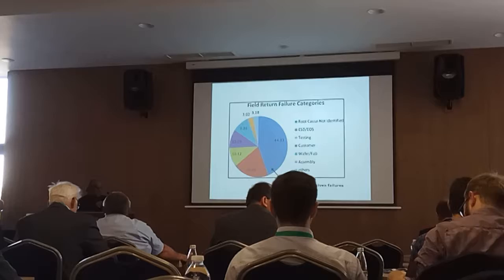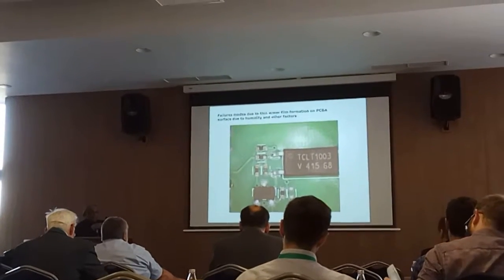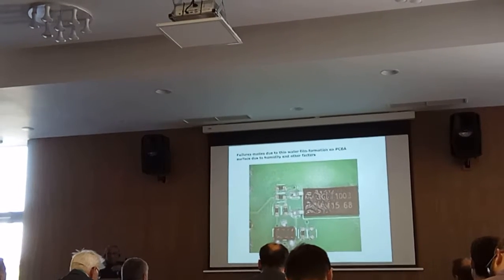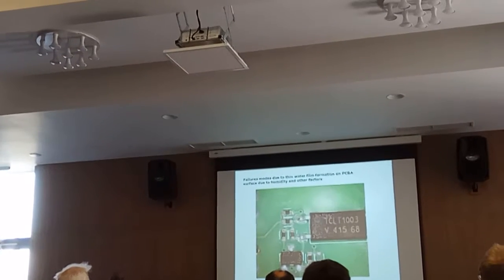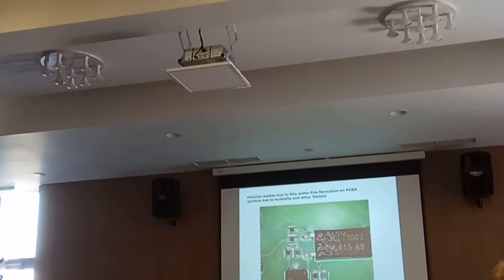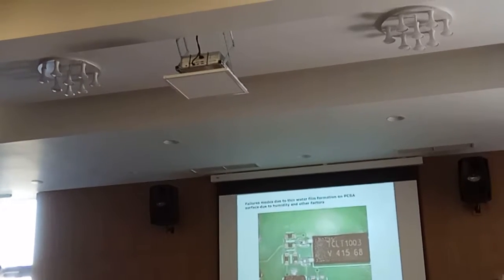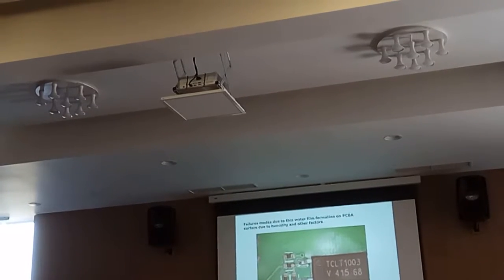When I say humidity-related issues of electronics, what I mean is that when the device is used at different places under different dynamic conditions where there are different levels of humidity, because of these different parameters, this humidity is forming a water layer on the surface. It may be a thin layer of water on the surface of the PCB, at least as a transient condition, and then it will cause a problem, because this water layer will act as a conduction layer, and it will create a surface insulation problem between different points.